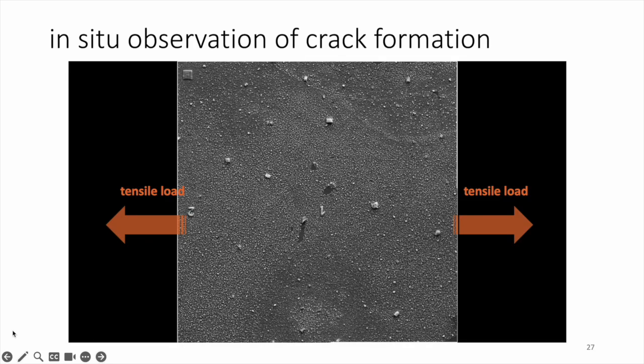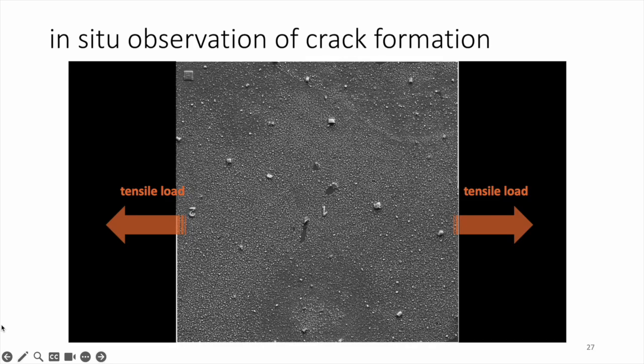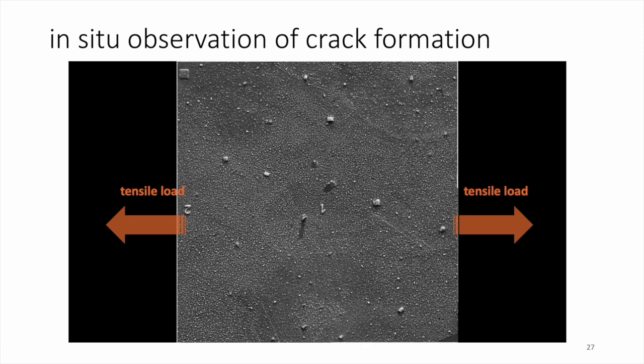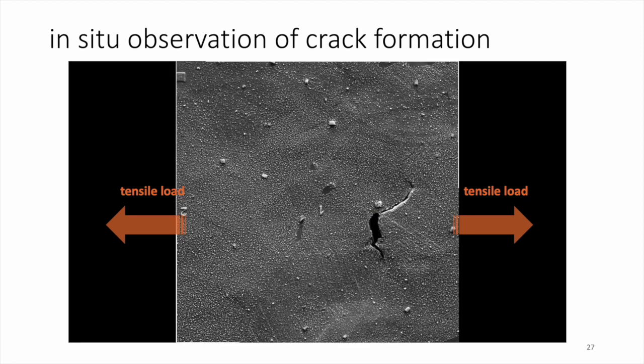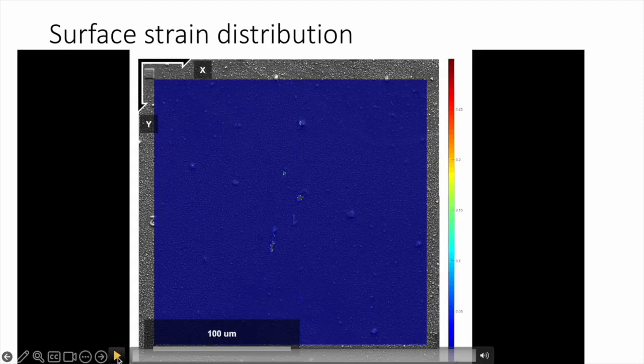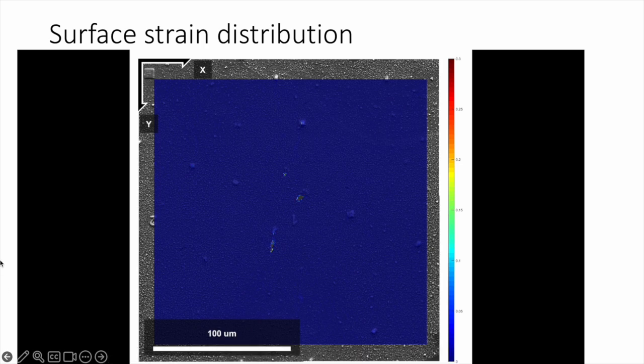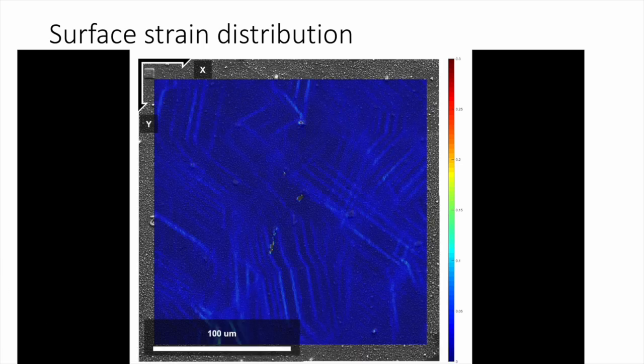As we keep on loading, we see some slip traces, and then we see just one of these cracks. This crack later on becomes our primary crack. I don't have another image because in the next frame it is completely broken, so I can no longer track it. We also did a surface strain distribution analysis of this part.